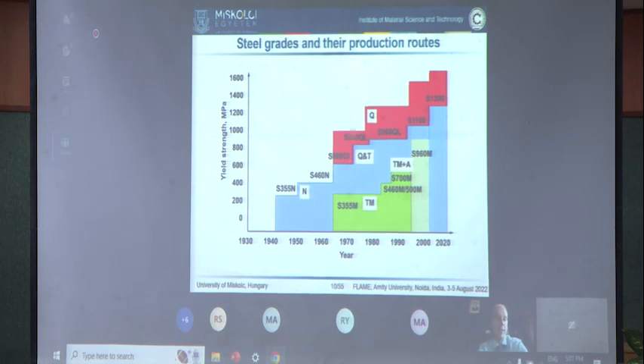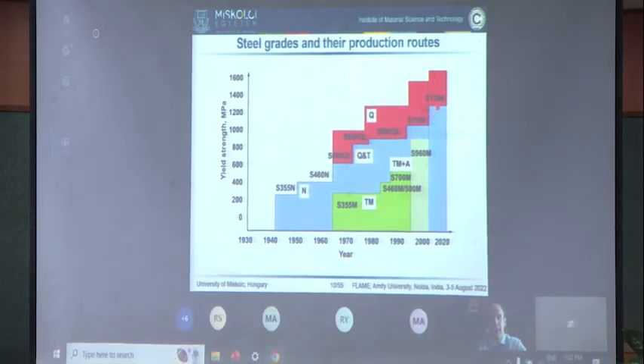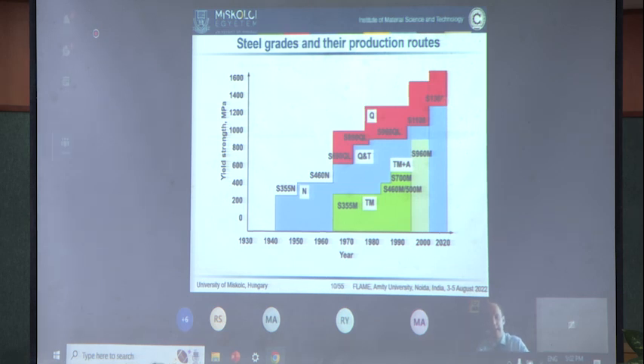In the mid 60s and around the 70s, the quenching and tempering process was introduced to steel production, and this is the real start of the application of high-strength steels. You can see that by quenching and high temperature tempering, today we can reach even 1,300 megapascal yield strength steels. However, I should mention that in terms of welding, matching type filler materials, when the weld has a similar strength as the base material, are only available up to 1100 megapascal. Besides quenching and tempering, the thermomechanical rolling process is a very good technology to increase the strength.